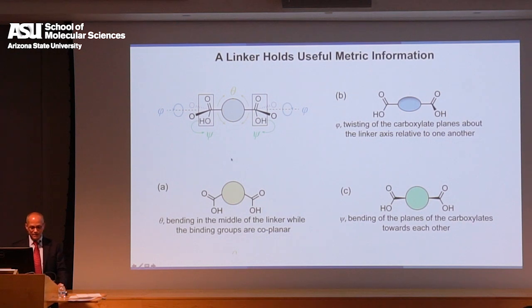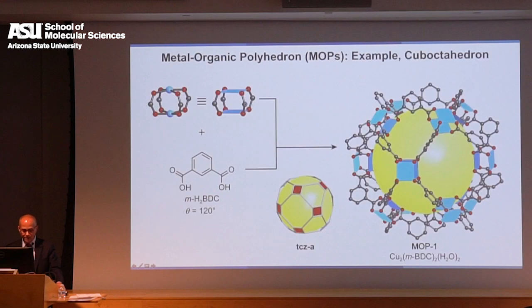The isophthalate, depending on the angles between the carboxylates, whether it's the bending angle, or the twisting angle, or the folding angle, they were all now important information that can channel you into the desired structure. And needless to say, we were able to make all of those. We made the bent structure, which puts the squares at 120 degrees together and makes the first nanoparticle that has been characterized by single crystal X-ray diffraction. Okay, so this is a truncated cube octahedron.